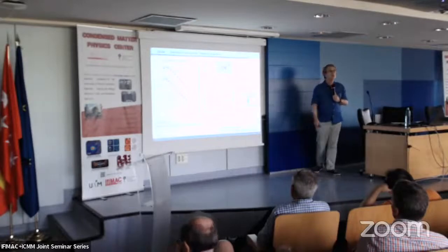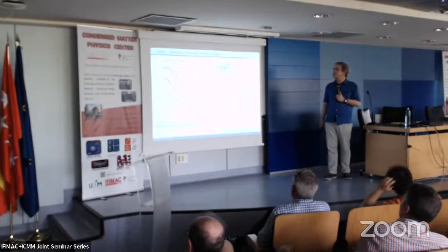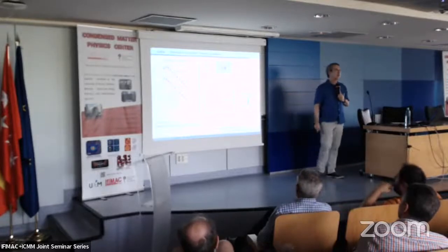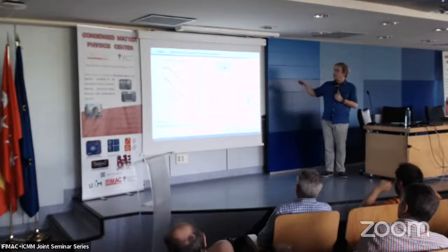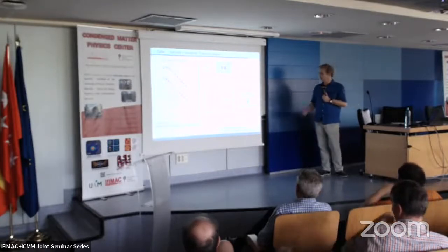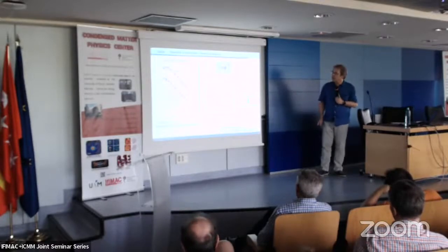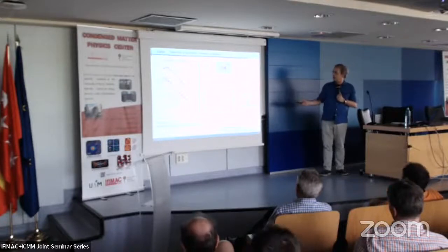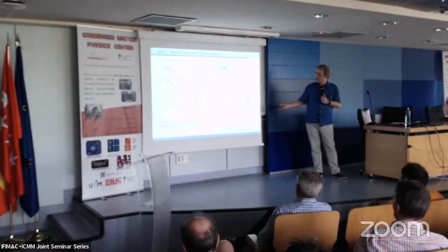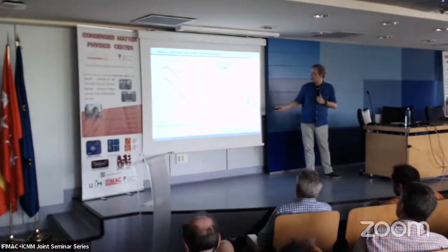Now the idea of provoking this strain, and eventually provoking single-photon emission like in the publication we saw, is, well, let's put a very small particle, what we will use is a sphere of 1 micrometer diameter, and then put a flake on top of it. It's a kind of image like a sheet going around this sphere. And the calculations of the band structure show us that in this system we can expect very long-lived excitons. That is due to the specific valence band structure, which is shaped like a caldera, so there is really no direct transition, but more indirect transitions, like an indirect exciton.